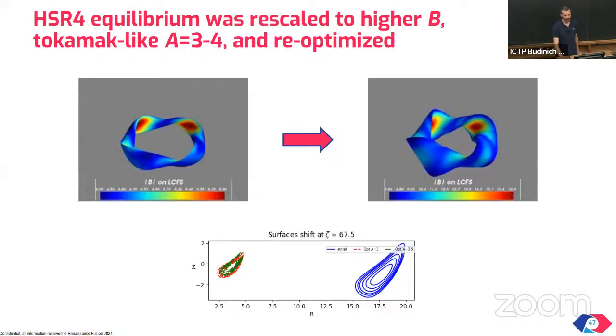Just a few quick words on recent progress, for example, in stellarator theory, in obtaining equilibrium between the kinetic pressure that tends to expand the plasma and the magnetic pressure that tends to compress it, for non-axisymmetric configurations of unusually low aspect ratio, between 3 and 4, so fat plasmas basically. So these are small in major radius, but they're fat in minor radius. This is exactly what you want for a compact reactor. You can see, by the way, the shrinking from standard designs. So this is by a factor of 5 or so, as you see.